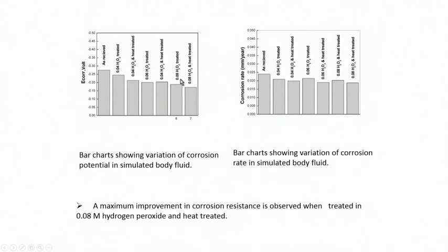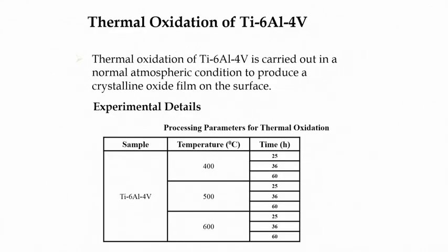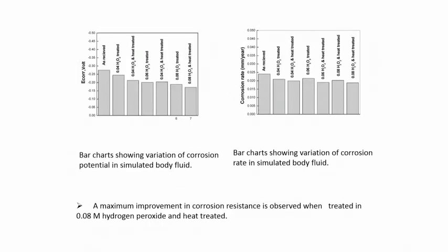but it was not really as high as desired, because this oxide layer was not really continuous. It was actually an oxide scale formed all throughout the surface in a discontinuous fashion. So, this chemical oxidation product actually offered very good wear resistance property, but for improved corrosion resistance possibly some other treatment would be required for full coverage of the surface.